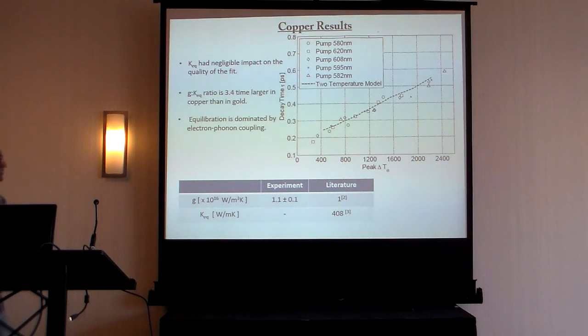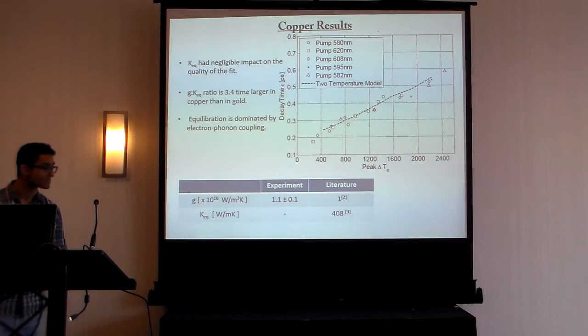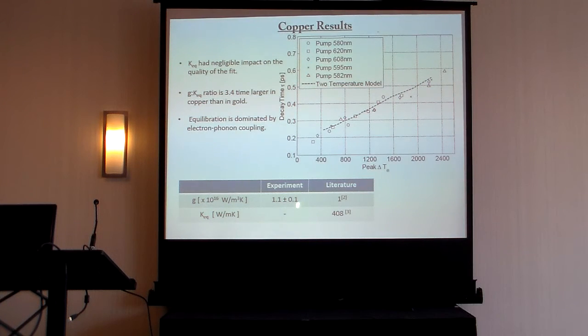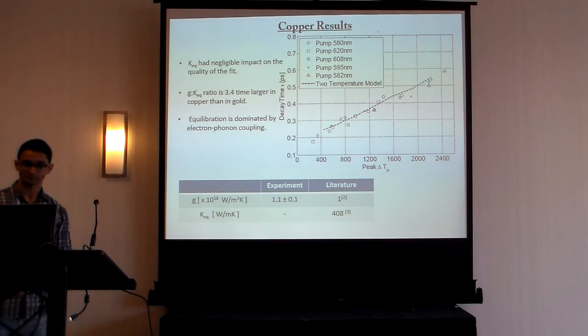Here we have our results for copper, and we found that in the case of copper, K_Q had a negligible impact on the quality of the fit. And this is because the equilibration process is largely dominated by electron-phonon coupling. Nonetheless, we still have good agreement with literature values for the electron-phonon coupling.